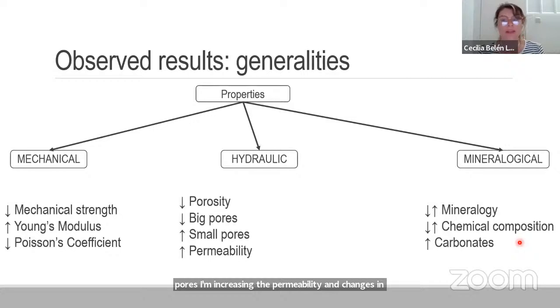The changes observed in mineralogy were mainly three. In the first place, we were able to see there were reactions between the CO2 and the plagioclase that produced, on the one hand, clay minerals that migrated and in some way ended in our bigger pores, which reduced the amount of big pores we had, also reducing the porosity and increasing the amount of small pores we have.